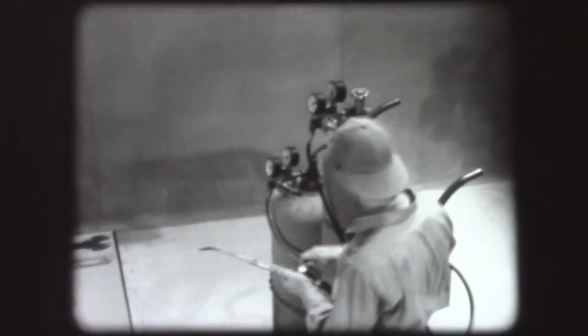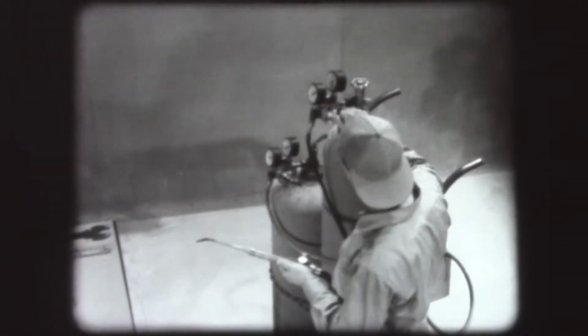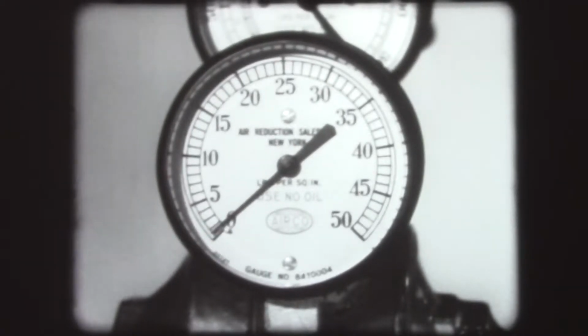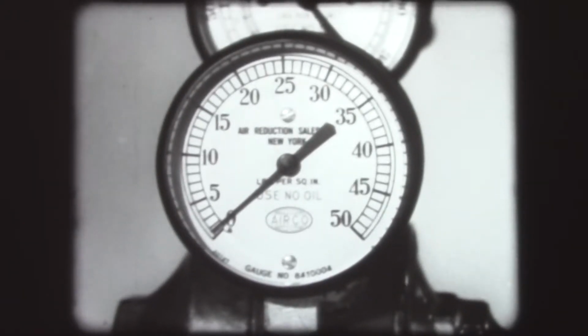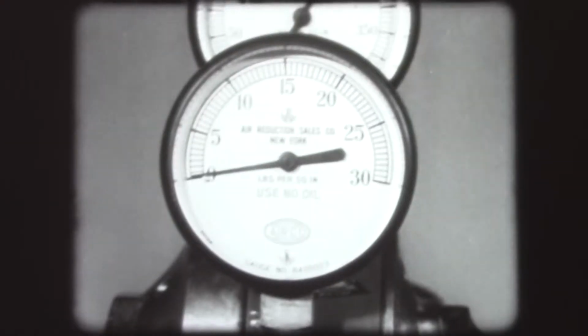To adjust the oxygen delivery pressure, open the oxygen valve in the torch. Turn the pressure adjusting screw until 1 pound shows on the gauge. Close the oxygen valve. Set the acetylene delivery pressure the same way, opening the cylinder valve 1 full turn. Never use acetylene pressures over 15 pounds. Turn the acetylene valve a full turn.